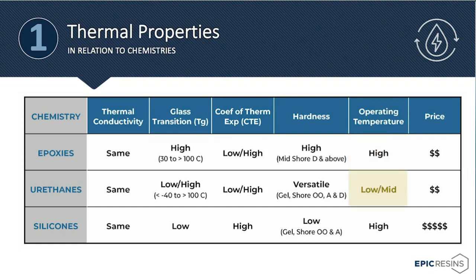Urethanes have a low to a mid-operating temperature range, and again, this comes from its ability to have higher cross-link density, but not quite as high as epoxies. Silicones have a little bit different chemical backbone, so that allows them to have high operating temperatures. Because of the nature of the pricing of silicones, epoxies and urethanes are excellent replacements for silicones in potting applications.